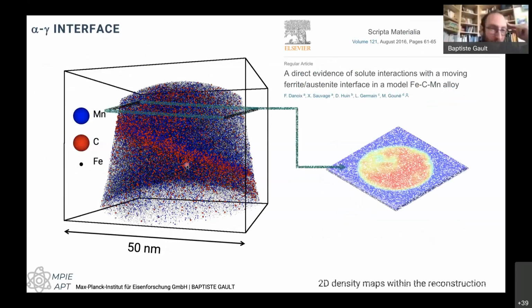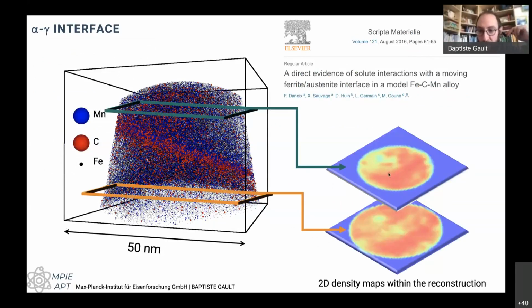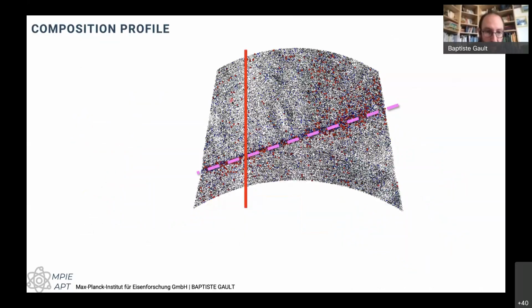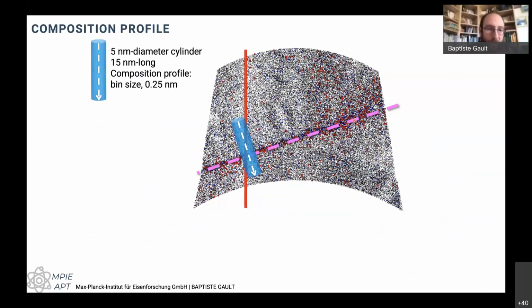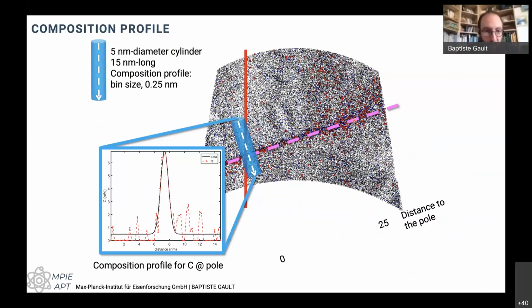I can look in the top grain and the bottom grain. I can see here that there's one of these regions that has a low density corresponding to a set of planes. It's actually continuing through this interface that was inside of the material. So I can look and see, you can see the planes here, they're well organized. And I can see how the resolution is going to affect the compositional measurement as I go through the entire interface. And so I did this, I just fitted a Gaussian to get some sort of value that made sense and get a full width at half maximum of the profile.